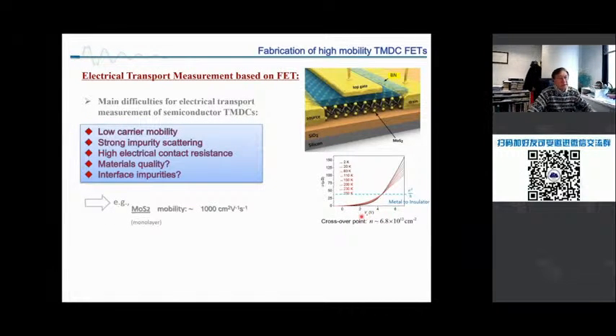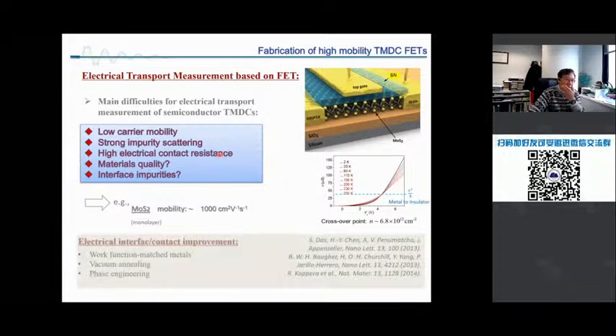Right. And so far, people, for example, study the mobility, the FET qualities. That mobility, compared to graphene, is too low. The mobility for graphene normally can reach millions, 1 million, in that range. But TMDC is too low. So what causes the poor quality of this device? There are a number of reasons, like the impurity at the interface, whether your sample is clean or not clean. Can you make a real ohmic contact to the conduction channels? Is this due to materials problems or due to the fabrication problem?